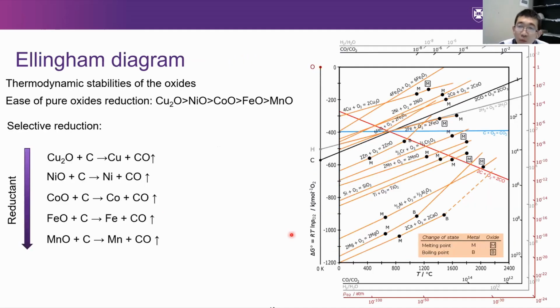So when we are doing high temperature processing, this is the basic principle of smelting reduction of oxides. It is called the Ellingham diagram, which is shown in this figure, and this indicates the thermodynamic stabilities of oxides. Basically, the oxide located in the lower part is more stable than the oxide in the higher part, and the carbon oxidation by oxygen line crosses the lines. So when this line is lower than the oxide, it can reduce and strip off the oxygen from the oxide.